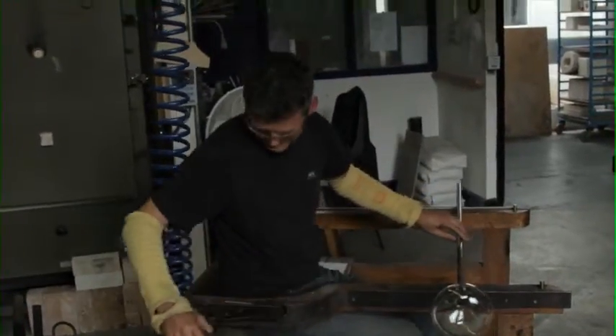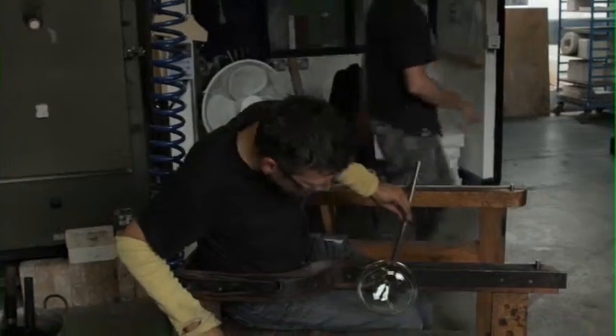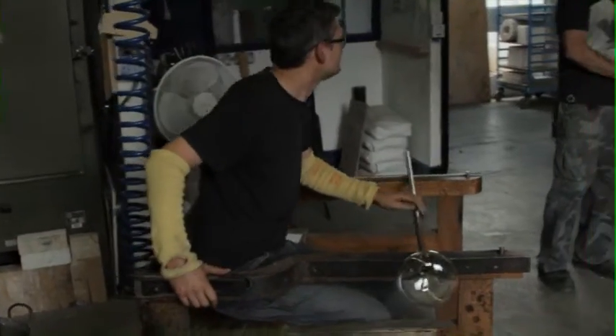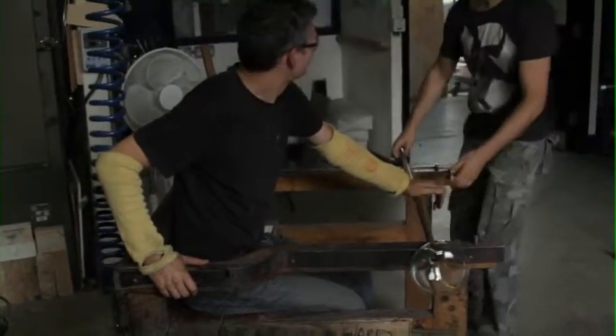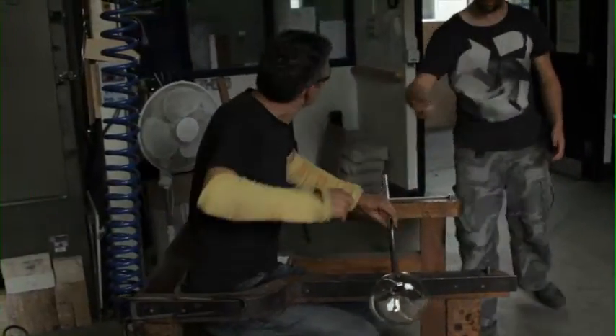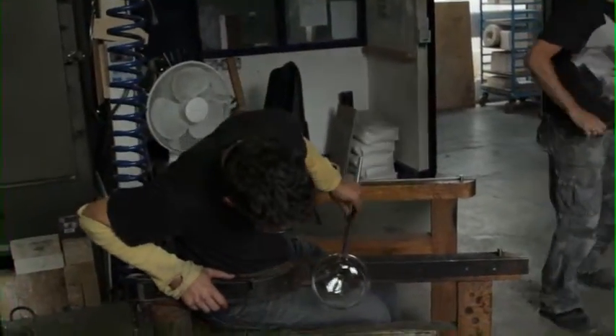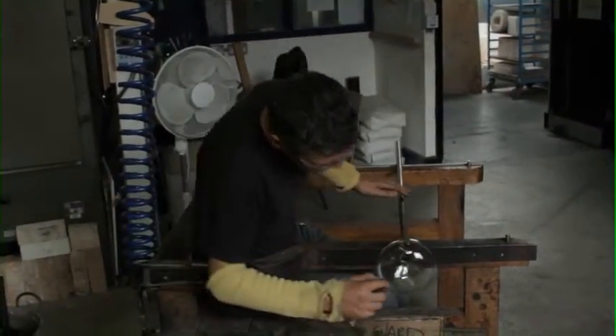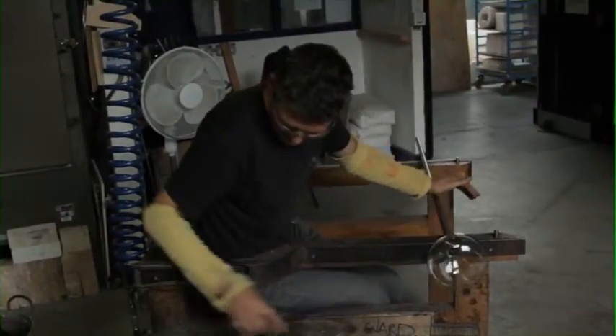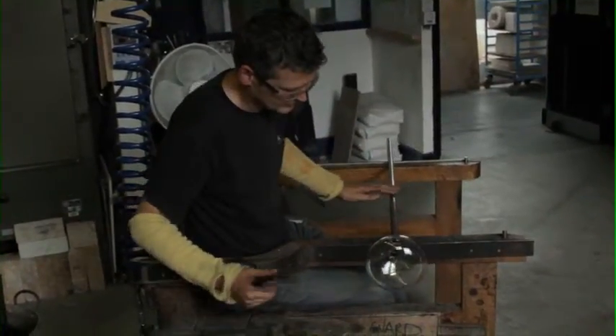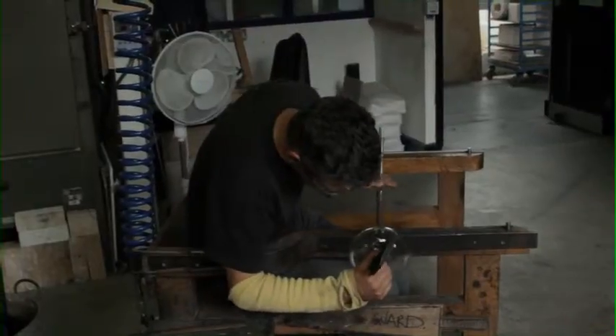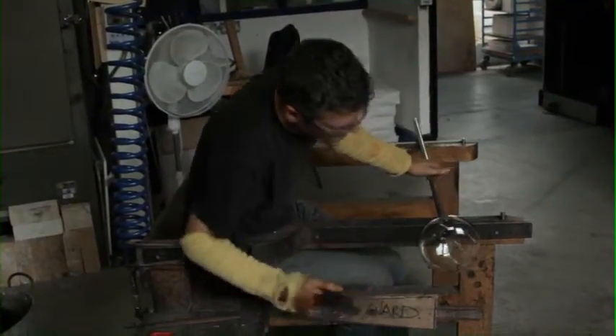Soda lime glasses tend to allow the glassmaker to blow thinner objects. It's much shorter than lead glass, and so loses its heat and becomes unworkable very quickly. Again the glass will fail due to thermal shock if it gets too cold, so that window of workability is reduced dramatically. The closest leadless glass to lead crystal in terms of how it feels to work with is Gaffer Glass.